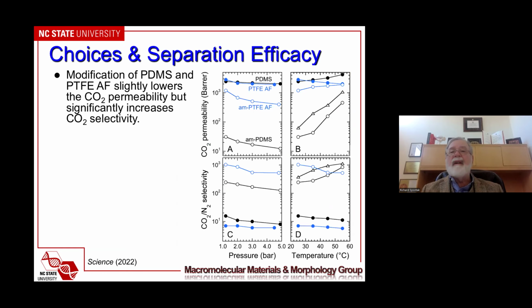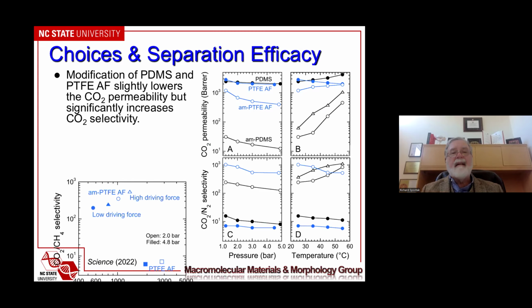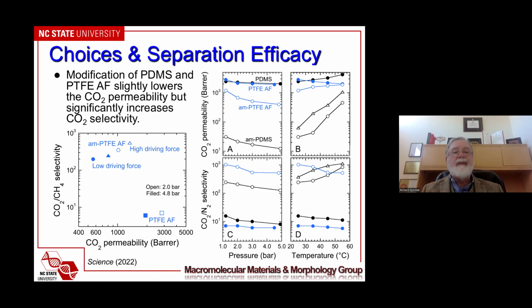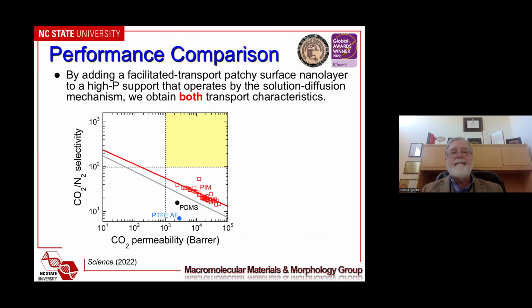Now, if we look at the performance, we see that initially the PDMS and PTFE have very high permeabilities, but very low selectivities. And after we aminate them, so that's what AM stands for, we see that the permeabilities drop a little bit, but the selectivities go up significantly. And we can do this also with CO2 and methane, and we see exactly the same kind of result. So it can be used for methane sweetening.